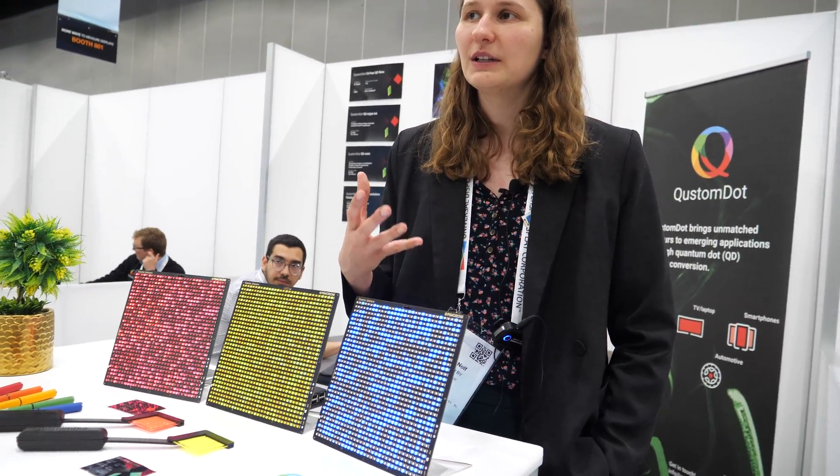And where are you based? We are based in Ghent, in Belgium. And how pure or stable can you reach? Is there chemistry in that? Yeah, there is a lot of chemistry in that — it's actually our patented technology. The stability of the quantum dots is very important because you want your device to last for a very long time. We define stability according to the light flux, and we say it's stable for hundreds of hours at a certain light flux. At this point we can reach half a watt per square centimeter for the greens and one watt per square centimeter for the reds, and this for hundreds of hours.